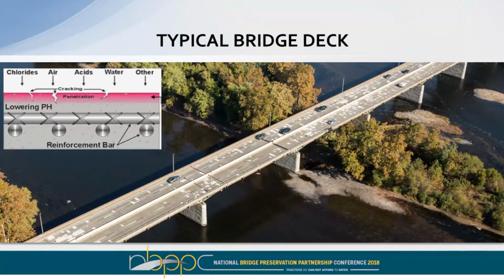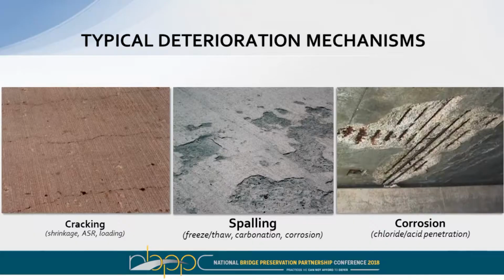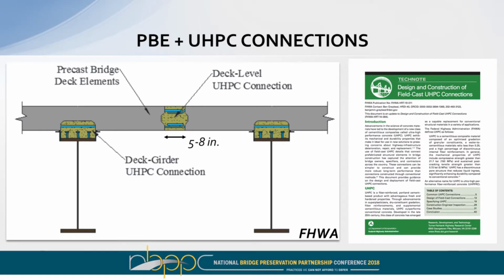So where this comes into play is when we look at bridge decks. Everyone here understands that they deteriorate quite quickly and they need repair and rehabilitation and preservation. And so UHPC overlay is one way to do it. If you let your bridge deck go too far, you end up having to replace the deck itself. And what you might have heard with UHPC before are precast connections. And that's kind of where this technology got its start here in the US, looking at full bridge deck replacements, putting in precast panels, and then gluing everything together with UHPC.